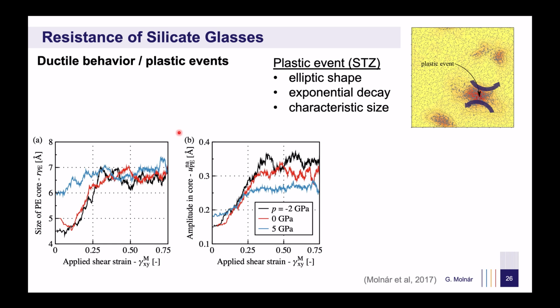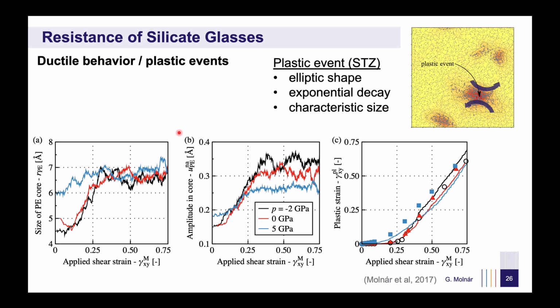At the atomic scale, we can directly observe the microscopic events responsible for plasticity in glasses, known as shear transformation zones. These plastic events involve local shear deformation with a volume change and exhibit an ellipsoidal shape and an exponential decay in strain distribution. This provides us with a second length scale, the size of these plastic zones, which we found to gradually increase up to 7 angstroms as the material transitions from elastic deformation to plastic flow. By summing the strain jumps in these shear transformation zones, we successfully recomputed the macroscopic plastic strain, confirming that these local events are indeed the fundamental carriers of plasticity in silicate glasses.